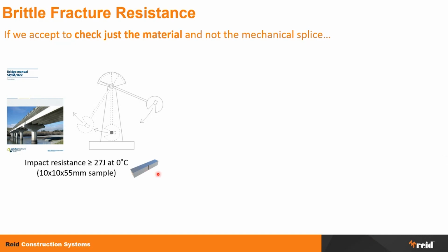How it works is that a little sample is cut out from the coupler when it's possible. Of course, it depends on how big the coupler is. If the coupler is small, that might be very difficult. The standard measure of the sample is 10 by 10 by 55. Then a little incision is cut in the middle, and this element is frozen to 0 degrees, and a pendulum strikes the sample. Depending on how resilient the sample is, it absorbs energy from the impact, and so the pendulum doesn't swing high after the impact.